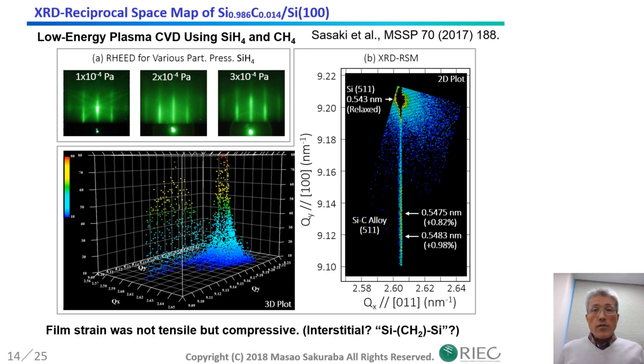In the same manner with the silicon-germanium alloy, we have also investigated silicon-carbon alloy epitaxy on silicon. These figures show electron diffraction patterns from silicon-carbon alloy films grown on silicon for various total pressures of silane and methane. These figures show 3D and 2D plots of XRD reciprocal space map for a silicon-carbon alloy film.